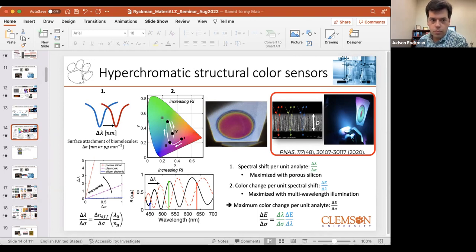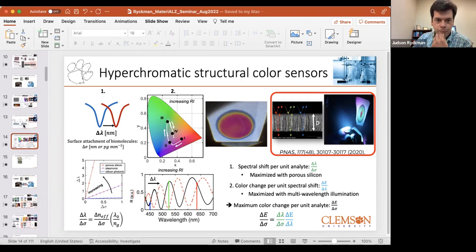When you have the adsorbates going in, it changes the refractive index essentially of the silicon oxide component, I guess. Is that right? And the silicon's not so important? That's right. I see. We'll model, say, this Fabry-Perot spectrum, and we'll include the N and the K. But the K won't really matter too much until we get to several microns. I see. Tens of microns.